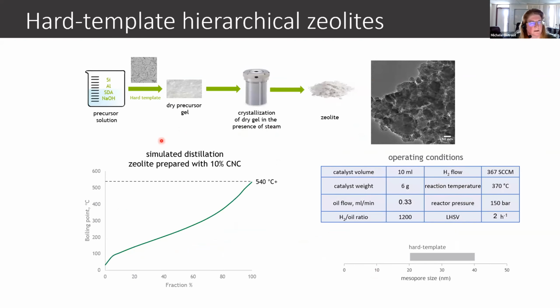So we developed a hard template hierarchical zeolite synthesis process where we take our precursor solutions, we add in our hard template. It goes through a dry precursor gel step, which then gets crystallized in the presence of steam, and you get your hierarchical zeolite. Some of our operating conditions are here. The mesopore size distributions that resulted from the beta zeolite included not just the micropore, the 2 nanometer pore size from the beta zeolite, but it produced the mesopore size of about 20 to 40 nanometers. But really very, very exciting is we were able to reduce the 540 degrees C weight fraction of our crude oil samples. 100% of it was converted, which means we were able to crack these very, very large molecules into molecules that were much more useful and could be put into additional downstream refining processes.